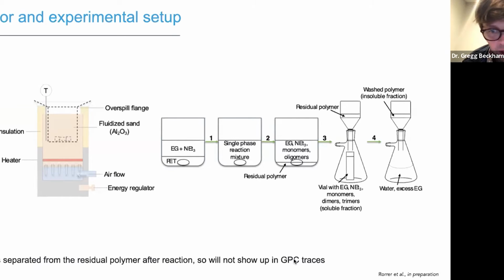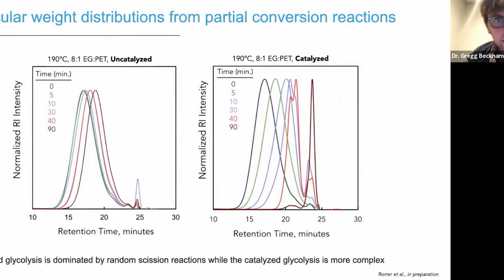I'm going to show you a lot of gel permeation chromatogram traces, and I just wanted you to note that in all of those, the monomer has been separated from the residual polymer after reaction. So just so you're aware in the GPC traces on this slide, these are essentially the molecular weight distributions from partial conversion reactions, going from 0 minutes all the way up to 90 minutes. You can see 90 minutes is the one here in dark brown.